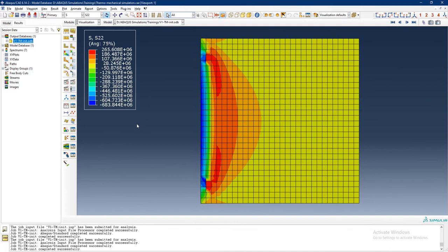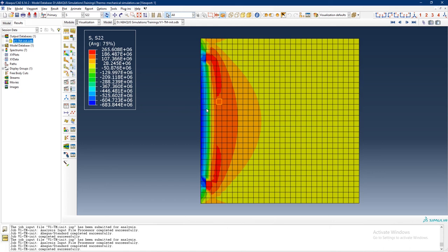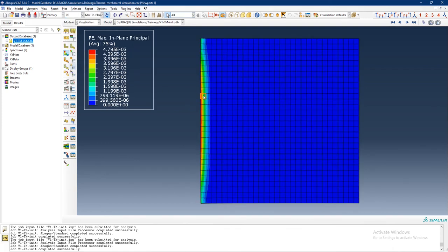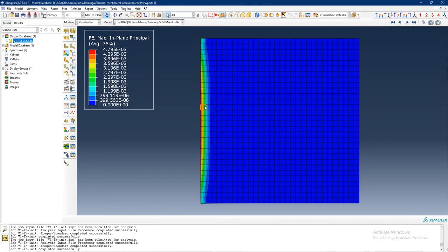We can also see the stresses in the y direction. Here we see that the part in the middle is under compressive load whereas the part below the surface is under tensile load. This is typical of the thermal load case. Due to this compressive load, the component here is undergoing plastic deformation. Due to this plastic deformation, if now I remove the thermal load, there will be permanent plastic deformation. The rest of the part, because it was elastically deformed, will go back to its normal state and then this area will be under tensile load.